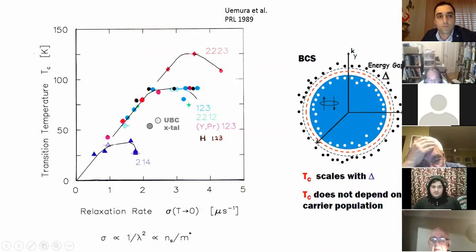So there is no direct dependence between the transition temperature and the superfluid density in the traditional BCS superconductors. Compared to this, our measurement, which we published in 1989, shows that these cuprate superconductors have a strong dependence between TC and the superfluid density, and so they are different from these simple BCS-like superconductors. This is probably the first signature that these new superconductors are different from the earlier materials.